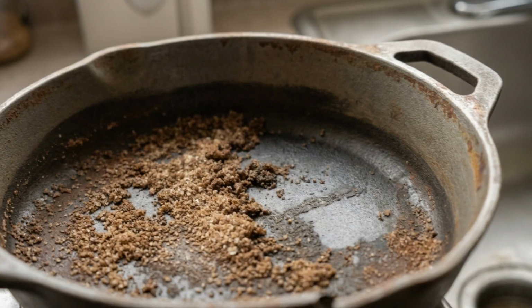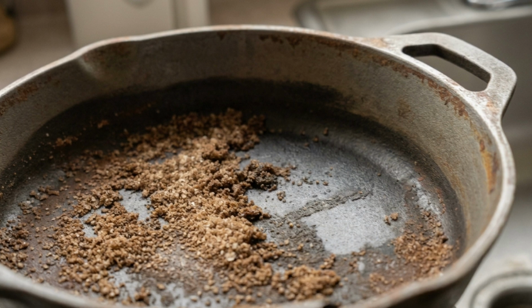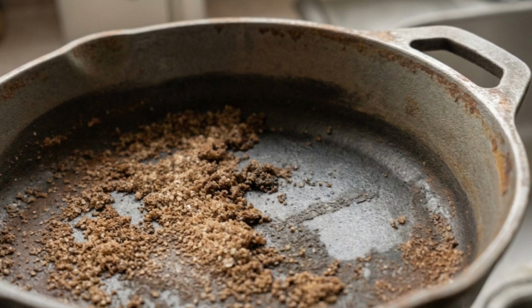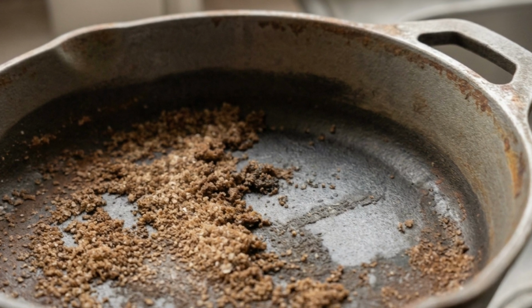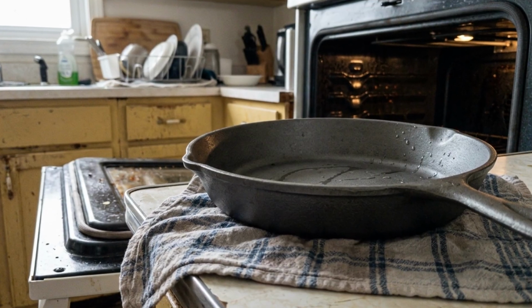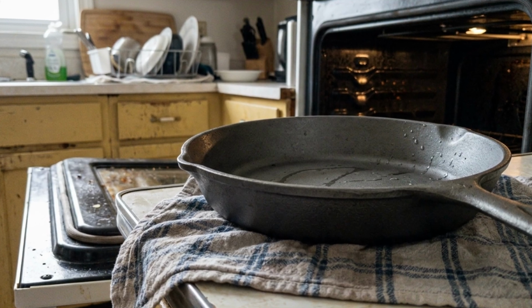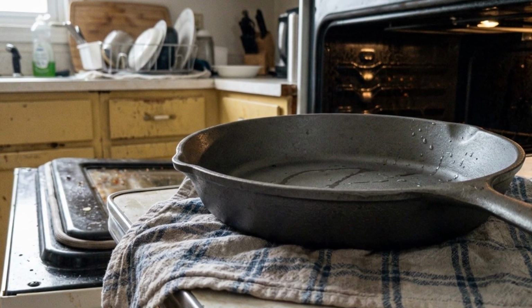We began by removing the corrosion. We refreshed the salt when it became brown with rust. We worked the inside, walls, rim, handle, bottom, and edges. We used steel wool for stubborn spots the potato scrub did not finish. Then we rinsed away the debris, dried immediately with a towel, and used the hot oven for about 5 minutes to chase out hidden moisture. Only after the iron was clean and dry did oil touch it.